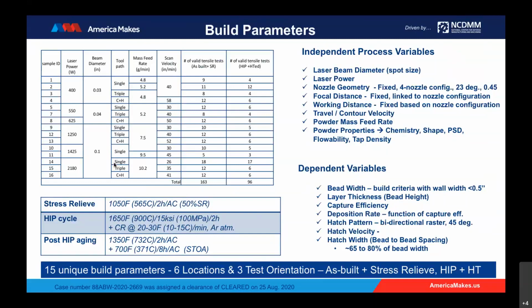So when we liberate the part from the substrate, it shouldn't crack, but it should have, so the stress relieving should be enough to not crack the part when you relieve it from the substrate. But at the same time, it should not forget the microstructure that was generated during the solidification and post solidification solid state transformation processes. And then the HIP and the heat treatment was done by a standard Ti-6 heat treatment as per the titanium handbook requirements.